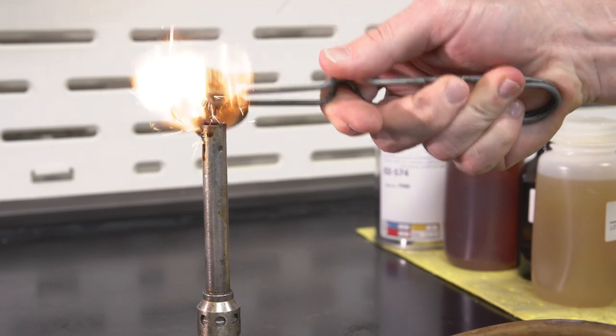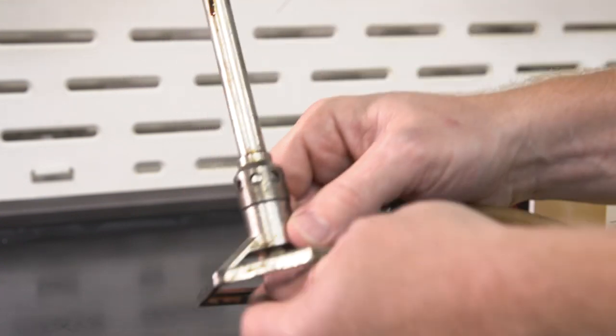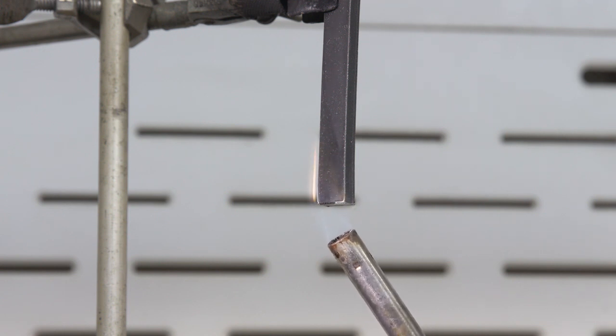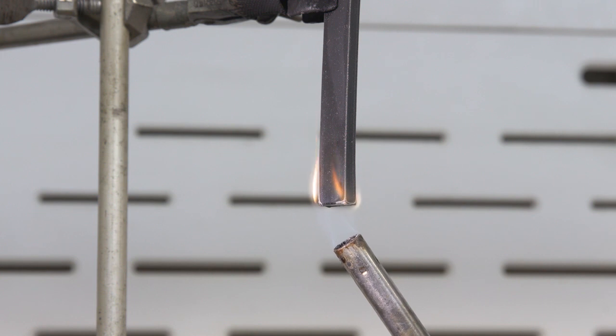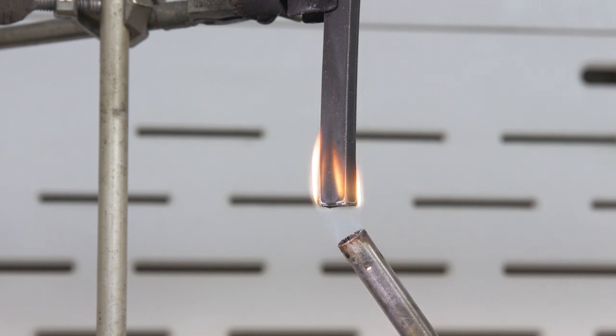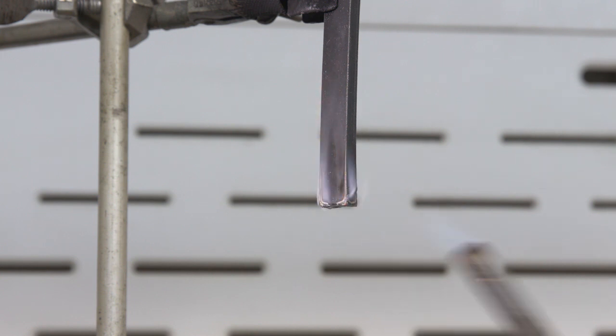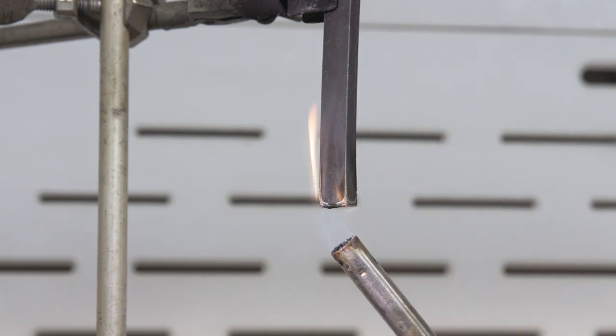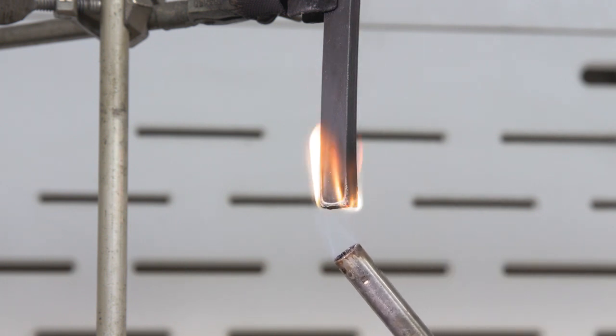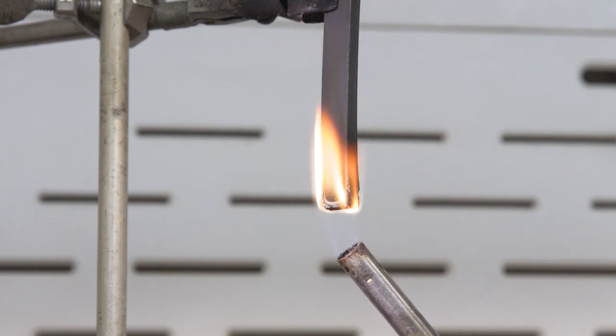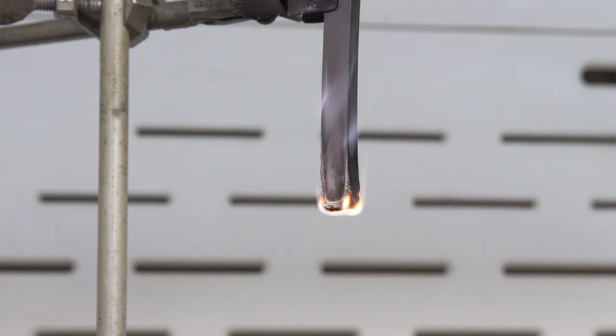Here is an example of the UL 94 V0 test using EPIC RM 2018. The flame is incident on the bottom of the vertical sample for 10 seconds and then pulled away. When it extinguishes, the flame is put back under the sample for 10 seconds again and then pulled away. The after flame time after each burn is recorded. As you have seen, the potting compound is burned as described and extinguishes in less than 10 seconds combined for both burns.